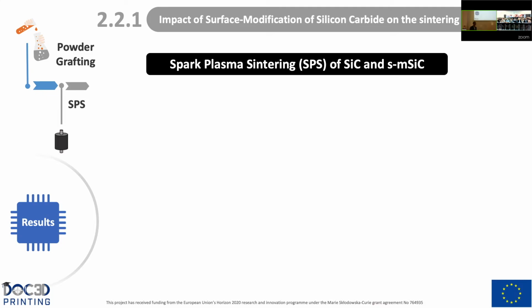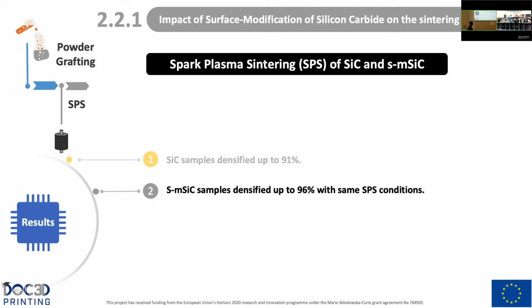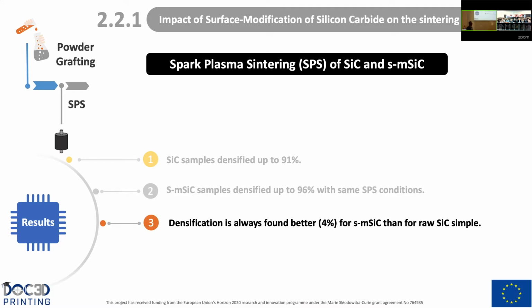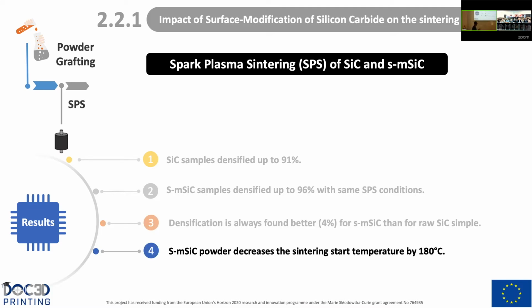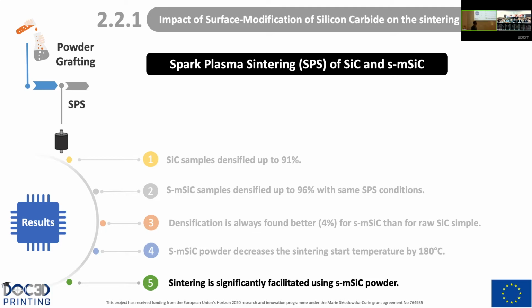So from this part, we can obtain the following results. First, we have densified a silicon carbide sample up to 91%. On the other hand, surface modified silicon carbide densified up to 96%. Remember, with the same sintering machinery conditions. Next, the densification is always better, by about 4%, for surface modified silicon carbide compared with the silicon carbide sample. And actually, the surface modification decreased the sintering start temperature by 180 degrees. And finally, the sintering is significantly facilitated using surface modified silicon carbide.